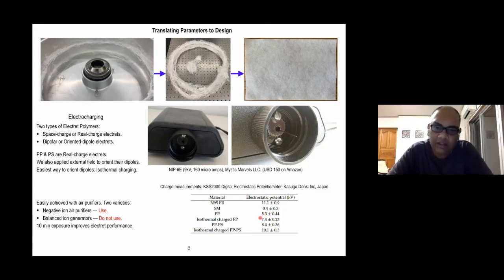And even here, the charge induced from isothermal charging would decay within 9 days, but if I put it in front of this negative ion purifier for 10 minutes, the charge would go up again. So just before giving it to somebody, we would charge it and give it to them and tell them that you should use it within a week. So there are many ways to do this. I just followed one way.